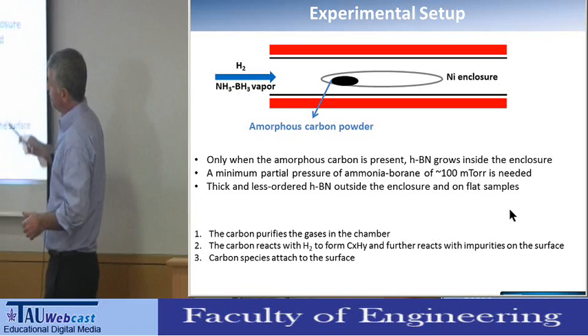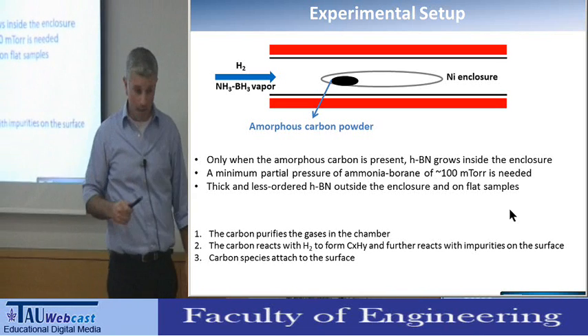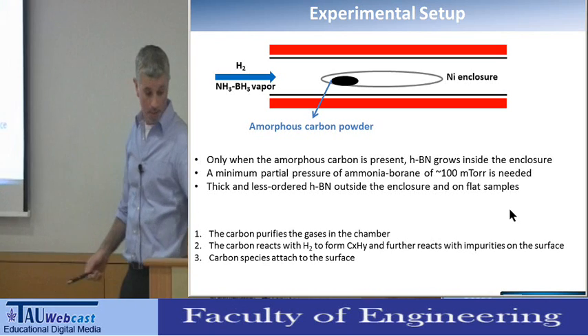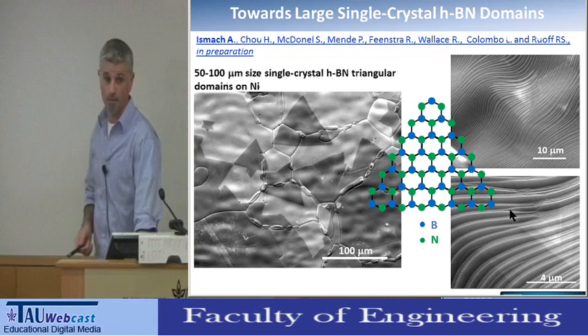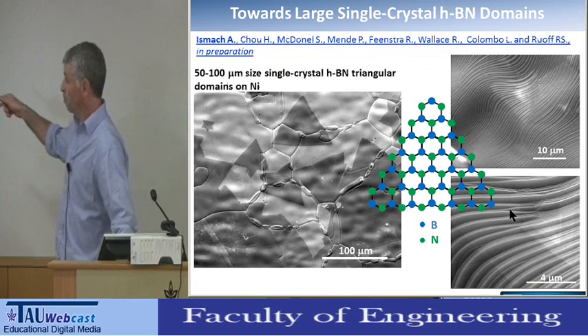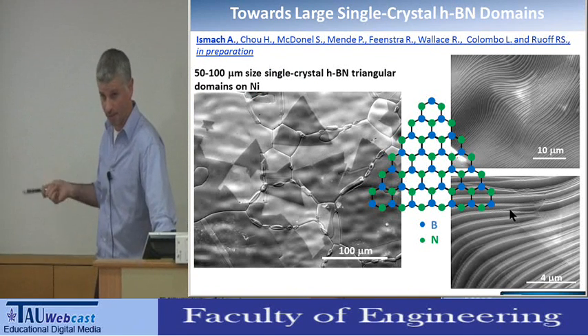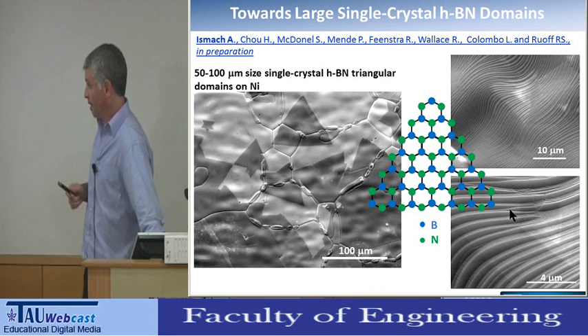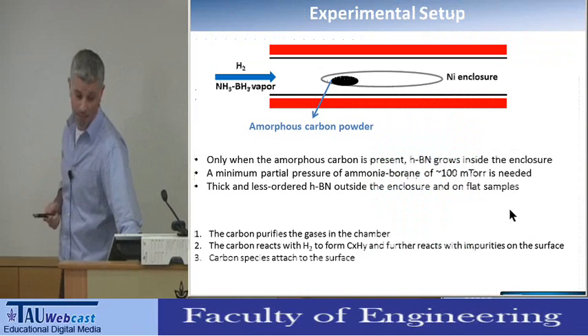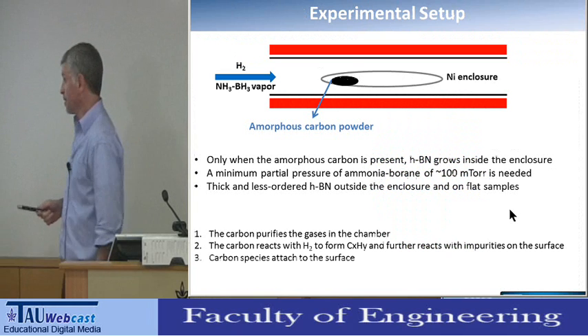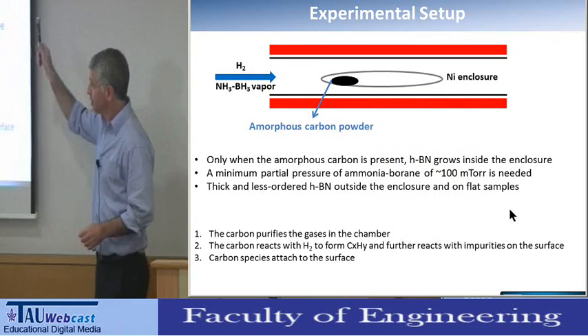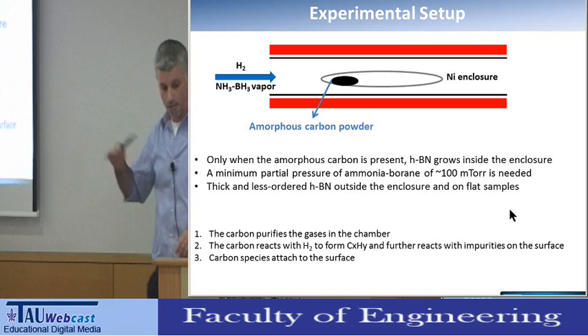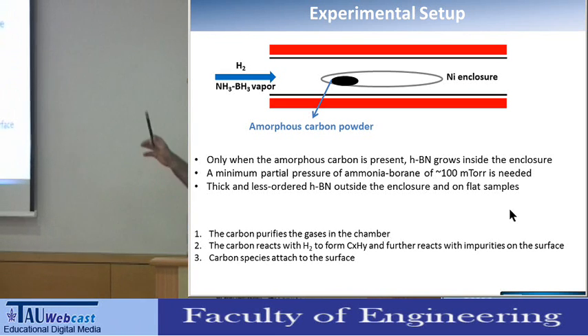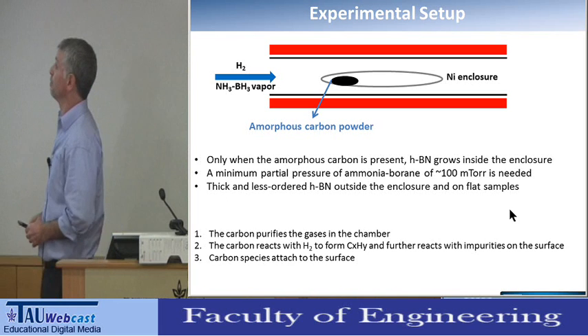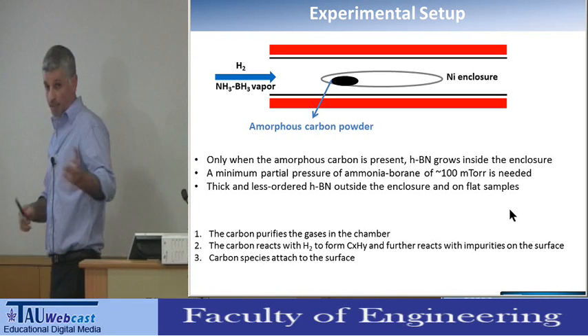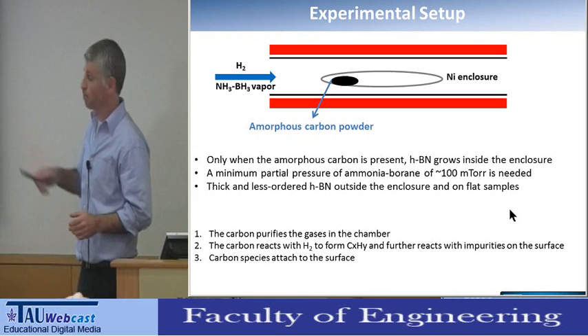But when I introduced some amorphous carbon powder in the pocket, we noticed that we can get these nice, large single crystals. We didn't know if they were single layer or bilayer, but I will show you in a minute that they are single and bilayer actually. And the reasons for that could be different. By the way, I did this experiment to achieve a different thing. I was trying to grow stacked layers of HBN and a few layers of graphene, and I will show you that I actually succeeded by different approaches. This is one of them.